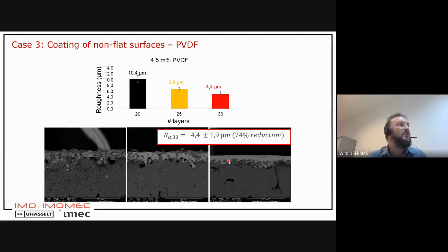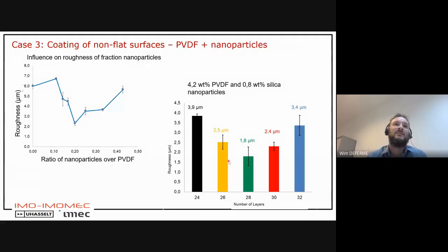But when we talked to industrial partners in 3D printing, they said that's not enough. If you want industrial grade, you need to go below 2 microns. So that's why we started adding silica nanoparticles. Here you have the number of layers and here you have the roughness, where we have 4.2 weight percent of PVDF and 0.8 weight percent of silica nanoparticles in our acetone. And then what you see is that after, let's say, 28 layers, we achieved a roughness below 2 microns, which is the industrial standard, as I explained before.